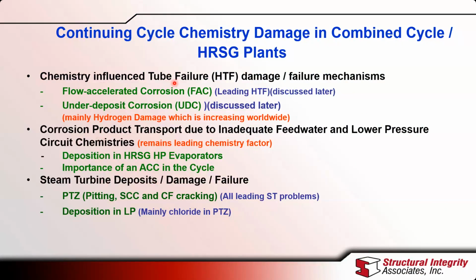First of all, of course, are the tube failures that take place. There are two main tube failures that we see all over the world. This one is flow accelerated corrosion, FAC for short. This is the leading HRSG tube failure mechanism, and we'll talk a little bit about that later. The other one is under deposit corrosion. We call this UDC, and this will also be discussed later. Mainly, we're talking here about hydrogen damage, and unfortunately, this seems to be increasing around the world.